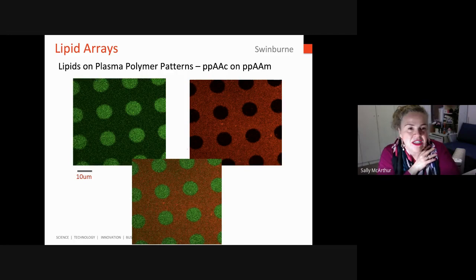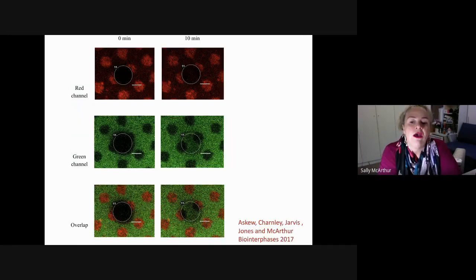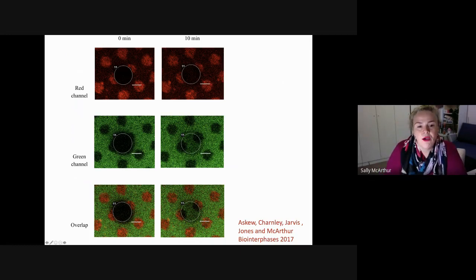And what we actually were able to show by photobleaching again was that the regions that we overlapped, and you could see that we've got migration of the lipid in the regions between, but where we've crossed over and photo bleached the areas that are sitting here that are the red lipid, there is no mobility.